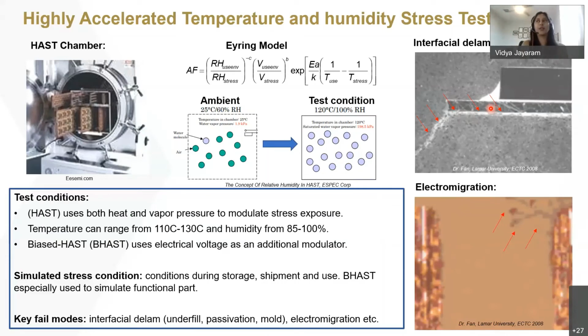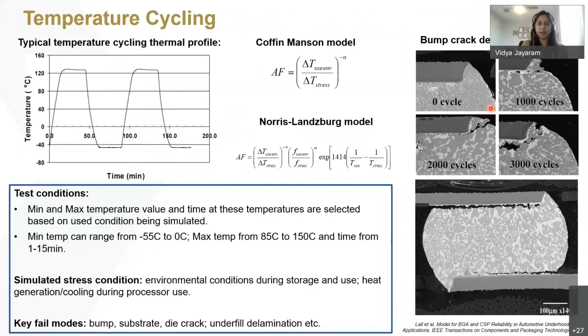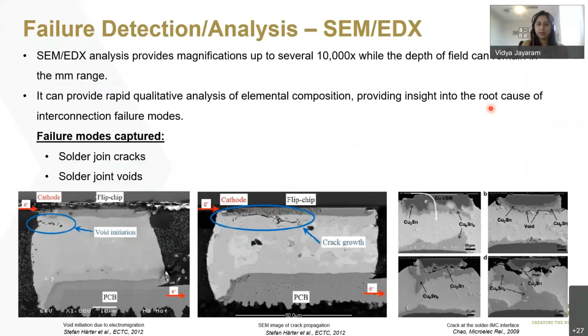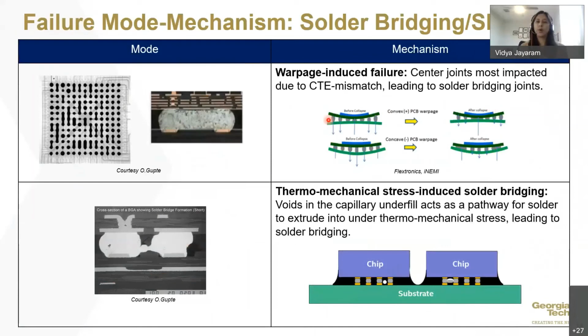When you talk about warpage induced defects, if you have, let me find the slide for that. Yeah. So when you talk about warpage induced defects, you have a tighter chip gap height at the chip level compared to the board level. So there is a higher likelihood that you will make the connection with some level of warpage at the chip level, which would be higher risk at a board level, where your sizes are larger, the pitches are larger. So you would see warpage related failure modes more on the board level interconnection side, with solder bumps bridging and warpage related non-wet.